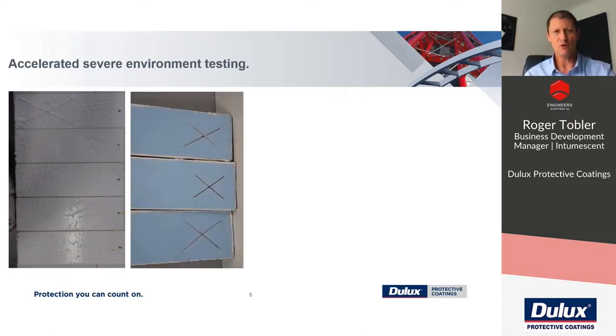On the second slide, we've gone to the opposite end of the scale. We've tested an epoxy intumescent. We've gone to 2,000 hours of testing here. That's 10 times what the panels on the left were subject to. And you can see virtually no blistering, no delamination, no undercreep. And that's with an epoxy primer, an epoxy intumescent, and a polyurethane top coat.